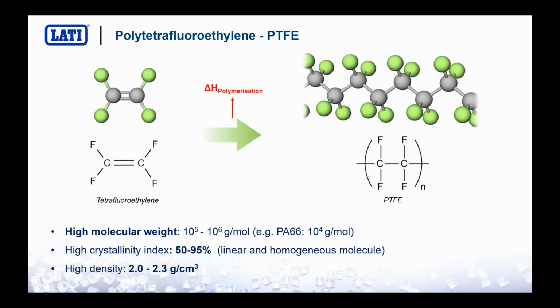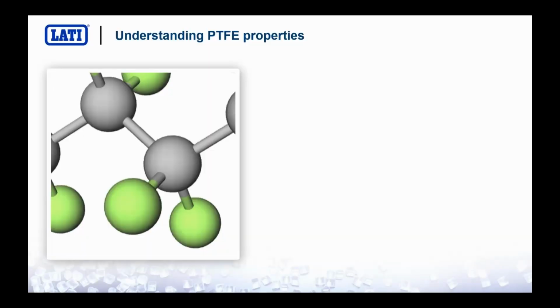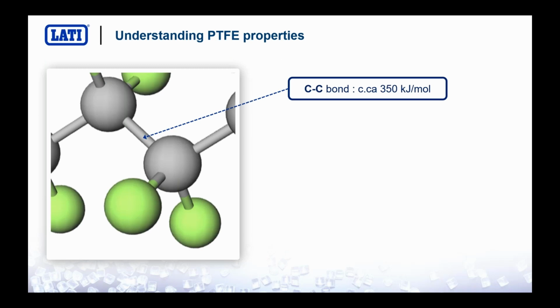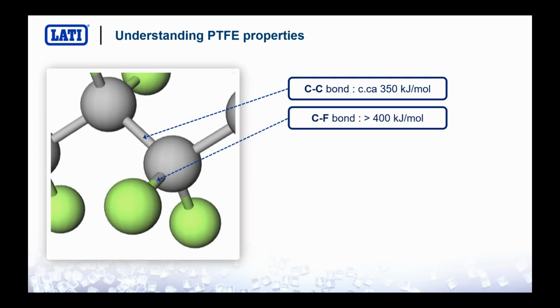We have to look a bit closer to the bonds of the PTFE molecule. Let's jump into the PTFE molecule. If we give a closer look to PTFE, we will find out that the carbon-carbon bond, the covalent bond between carbon and carbon along the backbone of the PTFE molecule, the gray spheres you see there, this bond is extremely stable. It requires more than 350 kilojoule per mole just to be broken. But it is nothing when compared to the carbon-fluorine bond. The carbon-fluorine bond is among the most stable covalent bonds that you can find in nature. Its energy is higher than 400 kilojoule per mole, and this is an extremely short and stable chemical bond.